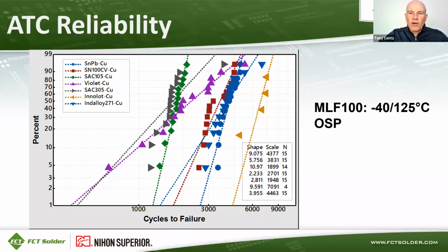So here's data for the MLF 100 with a temperature cycle of -40 to 125 C on an OSP finish. The different colored curves are, of course, all the solder alloys that were tested, and cycles to failure is on the x-axis. So the alloy that lasted the longest is the golden triangles on the right, which is Innolot. And then the blue dots and the blue triangles are tin lead alloy and Indalloy 271, which are fairly close. And then the red squares are SN100CV, which is solidly in the middle of the pack. And just for comparison, SAC 305 are the gray triangles, which are all the way on the left-hand side of this chart. So they had one of the lowest lives. So SAC 305 did not survive this test very well with that particular component.